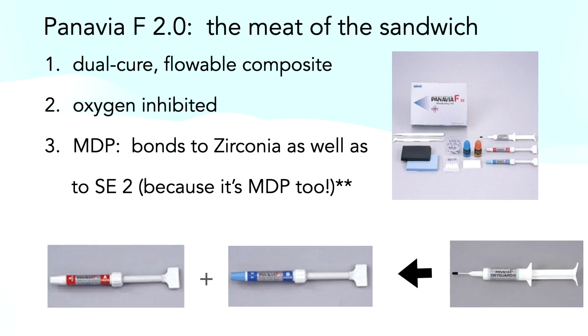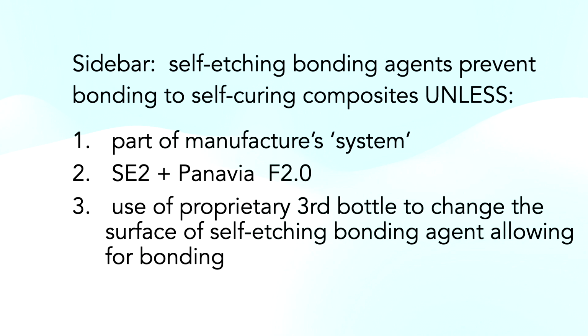And then once you get it seated, the nice thing about it being oxygen inhibited is that, especially if you're doing flat plane preps like me, orientation becomes a little bit of a bugaboo because you get the extra Panavia squirting out, and it's kind of hard to see your margins until you start wiping it off. So you can get everything oriented nicely and then squirt the OxyGuard on and start the initiation. Oh, okay.